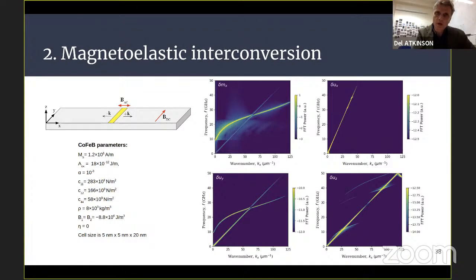But you need low damping. Is that right? Yeah. Is this a good material in terms of metallic ferromagnets? Is this a good material for low damping? Yeah, it is. Does it have the same value across all compositions of cobalt iron, or does it strongly depend on the composition? Yeah, it is strongly dependent on the composition. Right. So we can optimize the composition in order to achieve a lower damping. Is your composition optimized for that in this case? Do you know, or is it just random? This is probably one of the compositions that it was being compared to. These properties were taken from a low damping composition of cobalt iron boron.